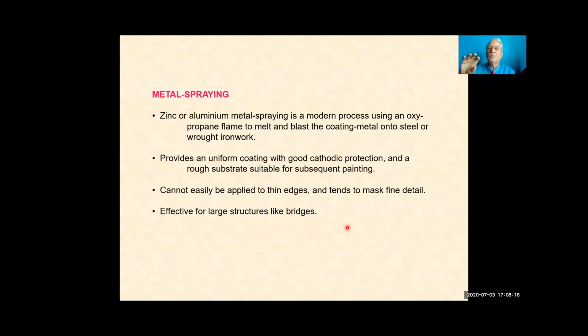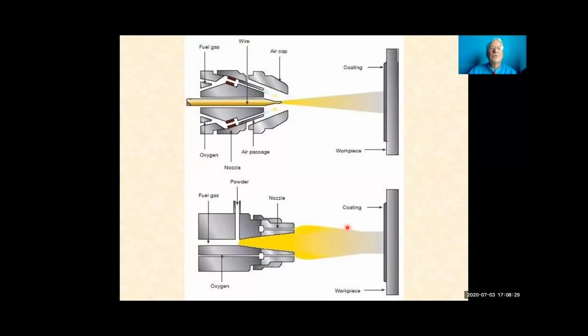It's not very easy to work on edges, and if there's a lot of detail, it's difficult to get it uniform. So it's good on sort of large structures. And this is the process. So you have a gun that has fuel gas and oxygen going into it, so you get a very hot flame here, and into that you feed a wire or a powder, and that melts the metal and it comes out as a spatter onto the very clean ferrous surface.